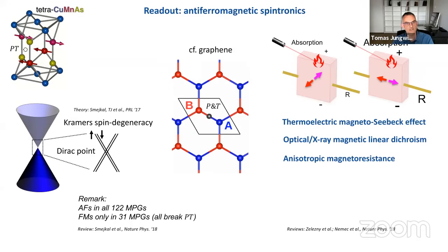And here, as an illustration of this principle, I'd like to emphasize that the PT symmetry, this was the symmetry that did not allow for the anomalous Hall effect, in fact allows for having a topological Dirac point in the electronic structure. Because if you have the combined PT symmetry, it guarantees that you will have a Kramers spin degeneracy of your bands. And if two such spin degenerate bands cross, you will get this topological Dirac point.